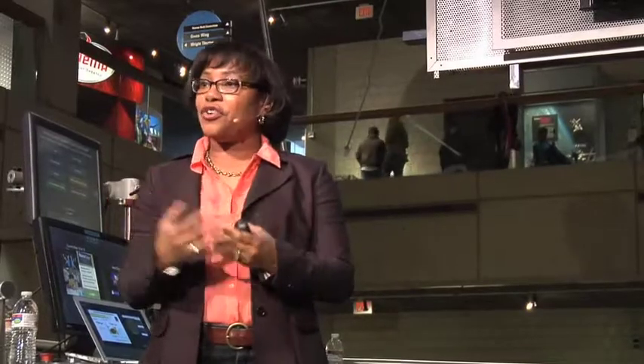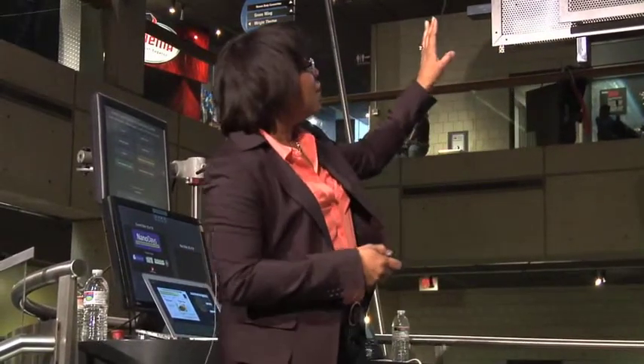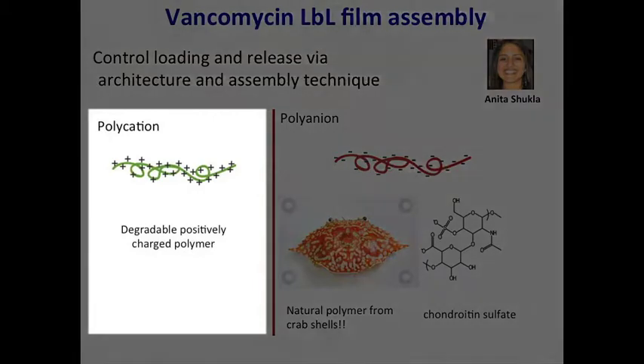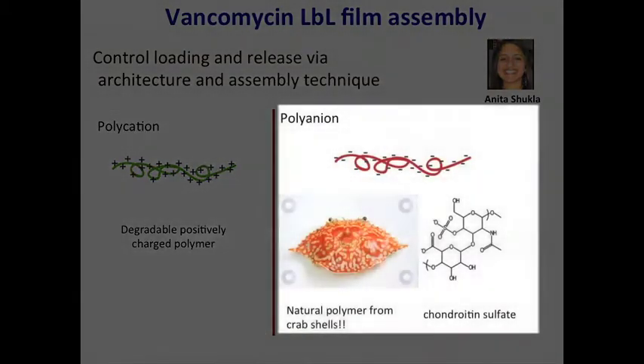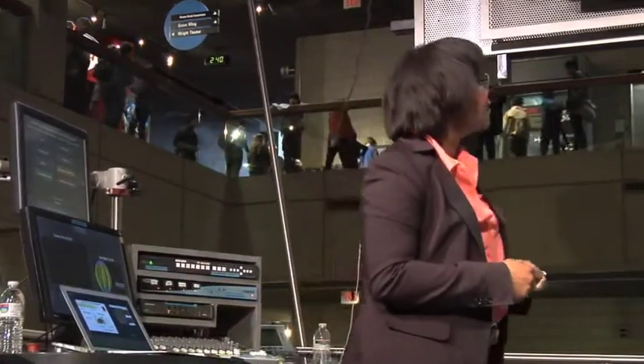What I'm going to describe to you are some of these methods. We have a way of incorporating these materials — we use a degradable but very biocompatible polymer that's positively charged. We can alternate that with a negatively charged polymer. That polyanion is one that is called chondroitin sulfate — you can see this in vitamin stores sometimes. It's actually a natural anti-inflammatory. You can get it from crab shells. These will be our building blocks, and into those building blocks we're going to incorporate our drugs.